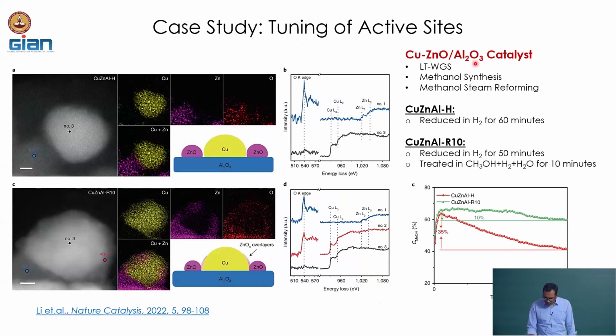Here I am showing an example of a copper zinc oxide catalyst deposited on alumina. This is a commonly used industrial catalyst for the low temperature water gas shift reaction, for methanol synthesis, as well as for methanol steam reforming. What we are doing here is two different types of treatment. In the first case, we are reducing the catalyst in a hydrogen environment for 60 minutes, and in the second case, we are reducing the catalyst in a hydrogen environment for 50 minutes, followed by treating it in a mixture of methanol, water and hydrogen for 10 minutes. And we have the high resolution TEM image on the left to see how these two different treatments ultimately result in a structural evolution of the catalyst.